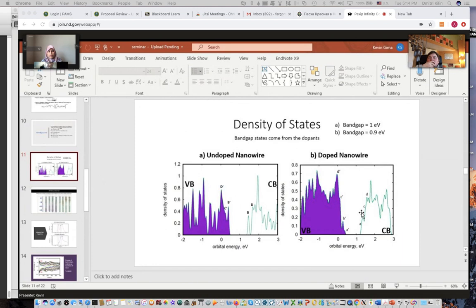And if you just qualitatively compare them, you'll see that the area for the valence band and conduction band is greater than that of the undoped wire. So that means there's a greater number of states available for the electron, and that means the measure of charge transfer has substantially increased for my doped nanowire.